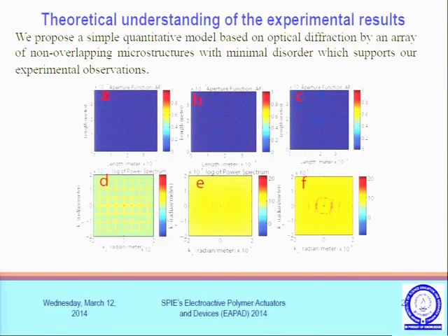But when we put, along with the shape and size noise, the orientation of the various portions of the microstructure arrangement, then this FFT gives the same result as we observed in the experimental finding. So this shows the role played by disorder in building up the diffraction pattern.